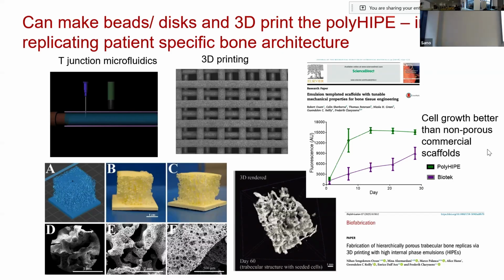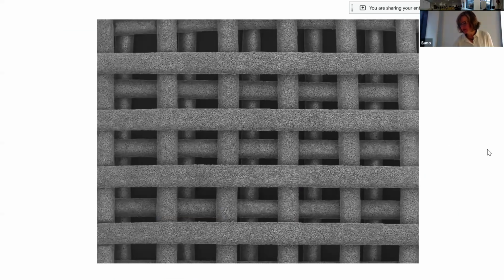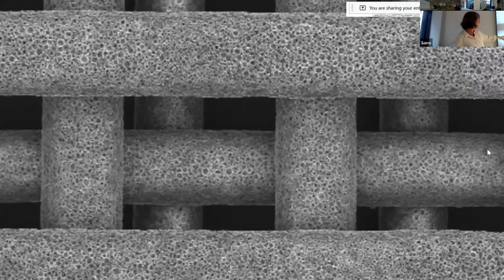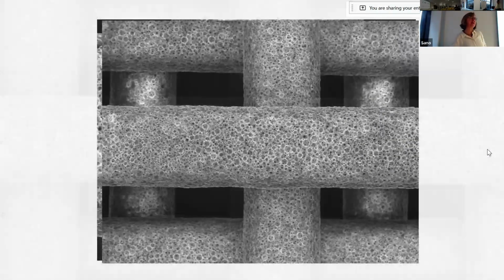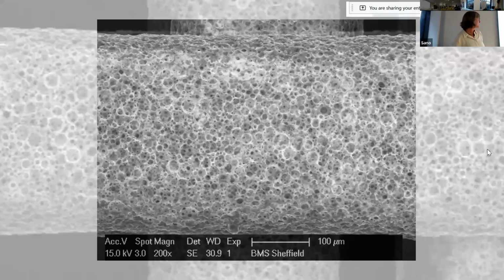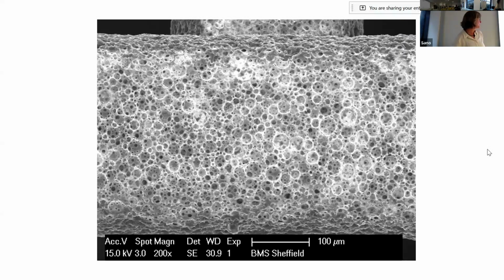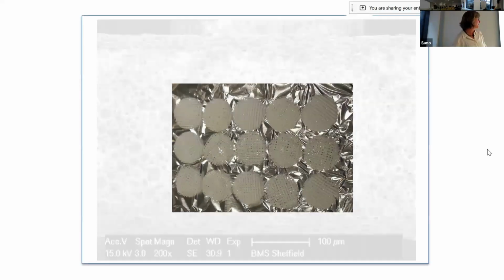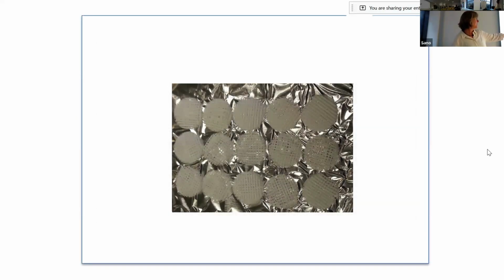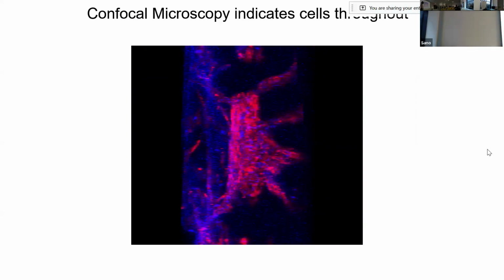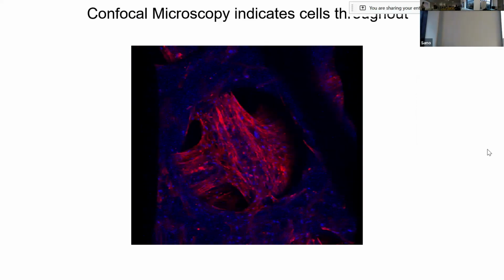So we can replicate trabecular bone structure, for example, from a CT scan provided in this case by Enrico. So this just shows you what this looks like zoomed in. So we can see that we have the printed 3D structure, but internal pores that are not printed but created by the fact that the paste was a HIPE, the ink was a HIPE. So we can get this multiscale porosity that's on the order of magnitude of bone scales, because bone scales are 100 to 500 for the bone marrow spaces and only about 10 or 20 for the cell spaces. So we can see cells grow on this really nicely because they can infiltrate both layers of porosity.